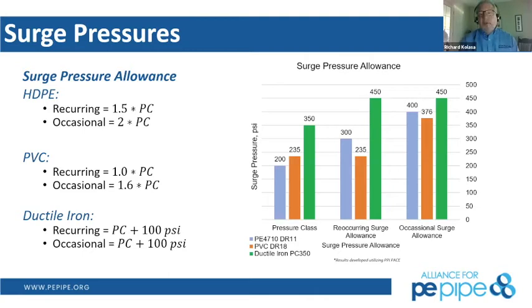So when we look at these values, we go, okay, how do we measure this and how do we protect against these surge events? Typically what we've done in the past is put some kind of design factor or dampening factor to protect the higher modulus materials, such as PVC. You have 1.0 times the pressure class. So if it's rated for 250 psi, you multiply by 1, well, it's still 250 psi. For occasional, they can boost it up a little bit because those rigid materials can handle it a bit better. Whereas the ductile iron has always had just this plus 100 psi occasional and recurring factor in this design.